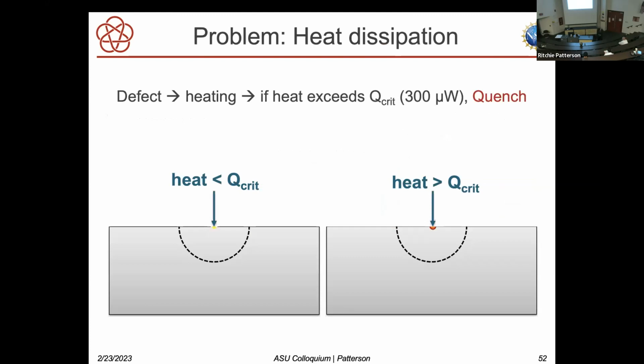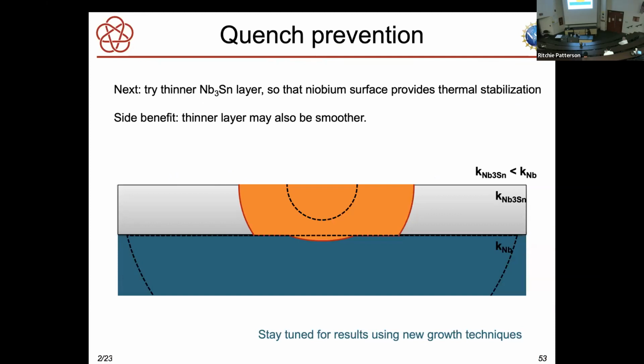Another problem that we have is heat dissipation. I said that thermal conductivity was low. So if you have just a small amount of heat, a hot spot on the surface, it can be okay. But if it gets above a certain threshold, then it spreads, and the whole cavity quenches. And of course, that then takes a lot of recovery. And so we need to prevent the quench.